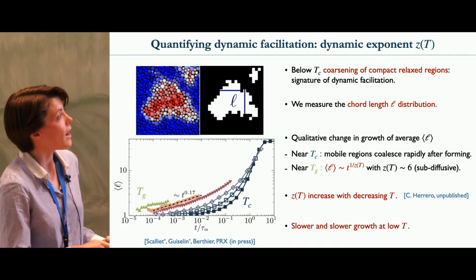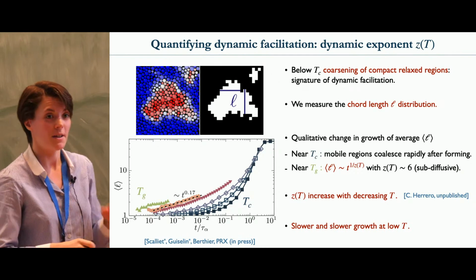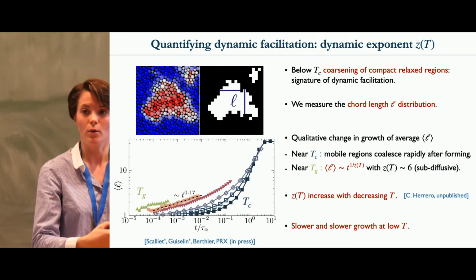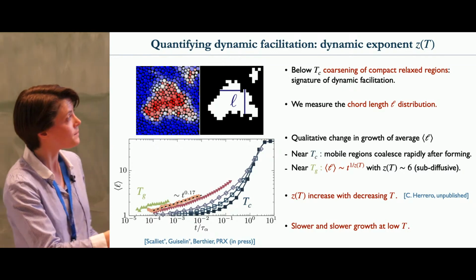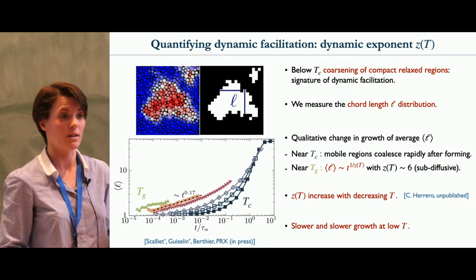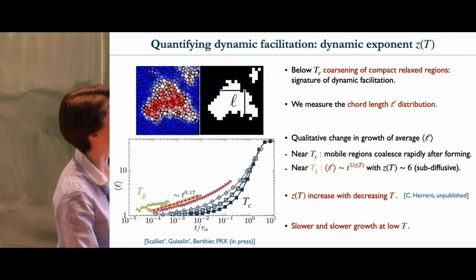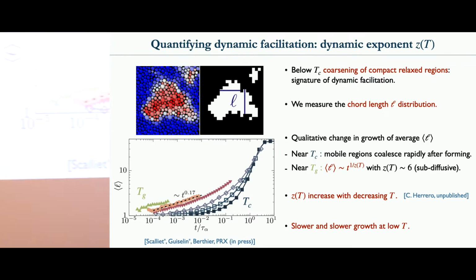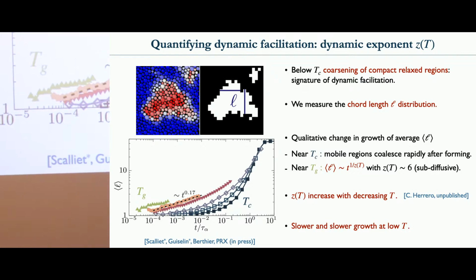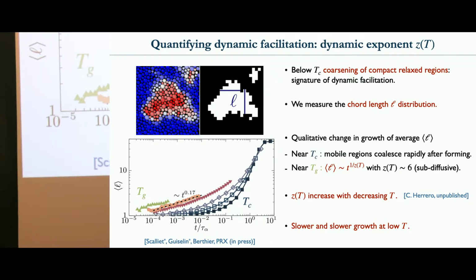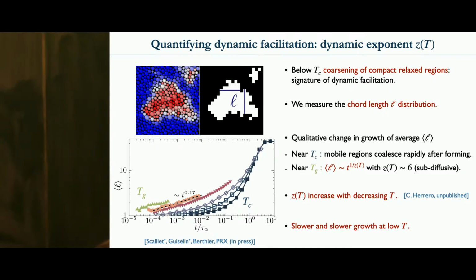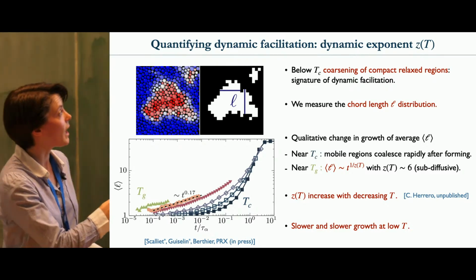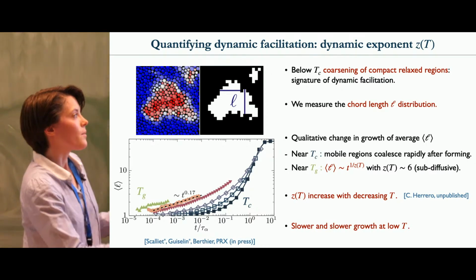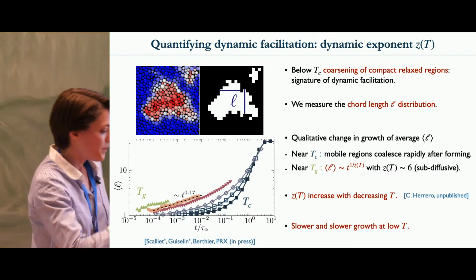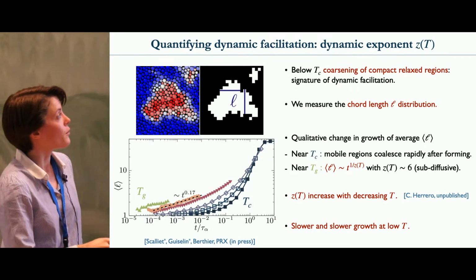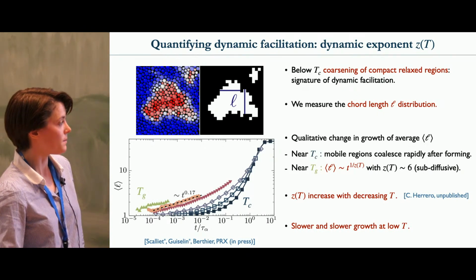So at low temperature, we have these compact regions, and I want to mention that this is not trivial. You really need to go to low temperatures to have this. And this allows us to directly quantify their length. With this chord length distribution, sorry, I don't want to go too much into the detail, but the idea is that now we can directly measure their length instead of doing some 4-point correlation or things like that. We directly have a length here. And we can measure this average length for the clusters as a function of time.